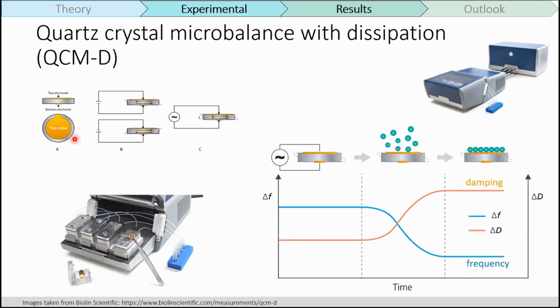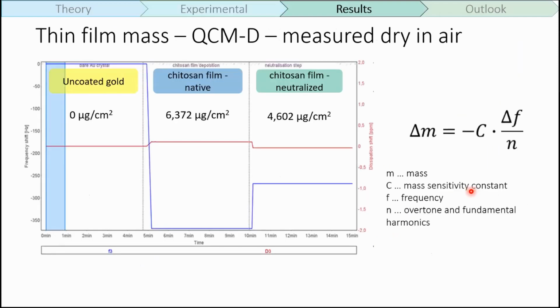It works upon a piezoelectric effect, which means that if you apply voltage, the crystal starts to oscillate at a certain frequency. With this frequency change, you can measure what amount of mass was deposited on your surface. And with the dissipation function, you can also measure the damping of your surface - for example, if your surface was very soft or very rigid, you would see it with this measurement.